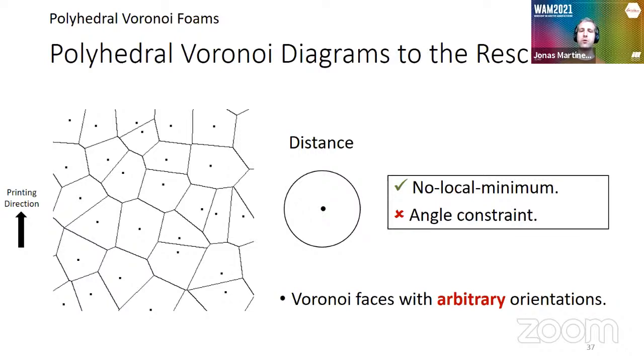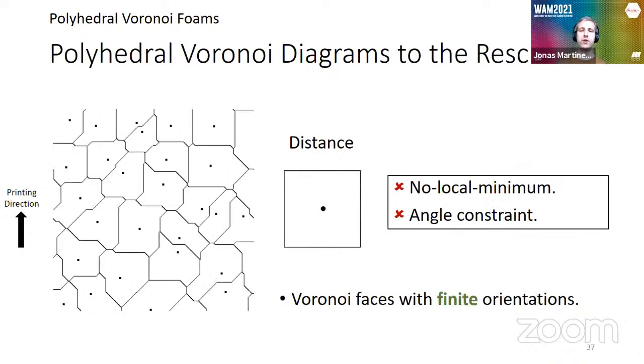So here's our intuition. We wonder, can we do something with the metric in order to ensure fabricability? Of course, with the Euclidean metric, it's not possible because the Voronoi faces or edges in 2D can have any arbitrary orientation. But if you change your metric to a polygonal metric, such as a square, here you can see something interesting happening. Basically, the edges of your Voronoi cells have a finite amount of orientations. Here, as you can see, it's either horizontal, vertical, or up to some rotation of 45 degrees.